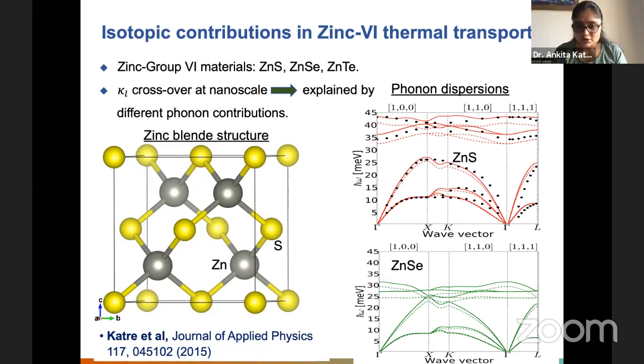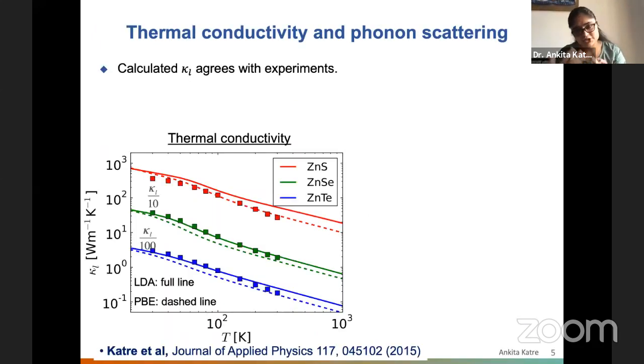Now, this is the phonon dispersion. Now we come back to another part, which is basically the thermal conductivity calculation. I'll come to the scattering part as well. So when we calculated the thermal conductivity, this is thermal conductivity as a function of temperature. Again, the full lines are LDA results, dashed lines are PBE results. I've scaled down the conductivities of zinc selenide and telluride by a factor of 10 and 100 to be able to see the plots clearly in this figure.